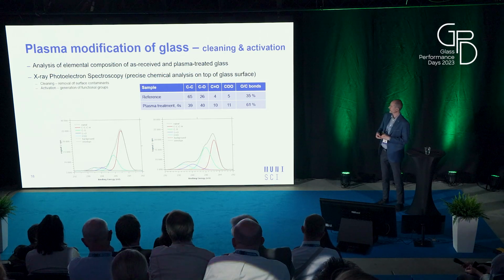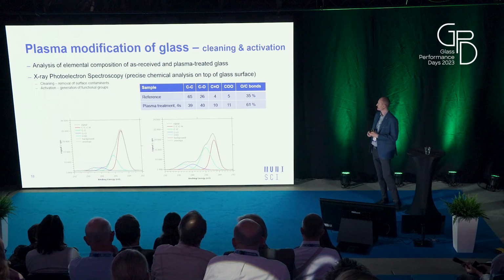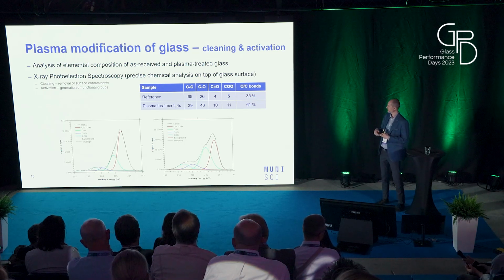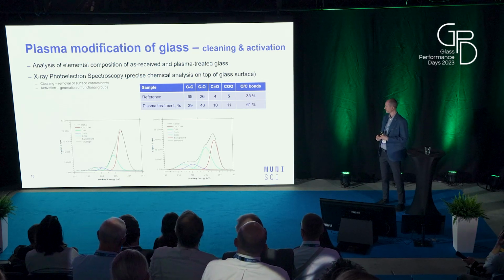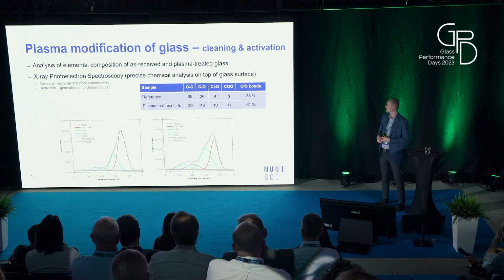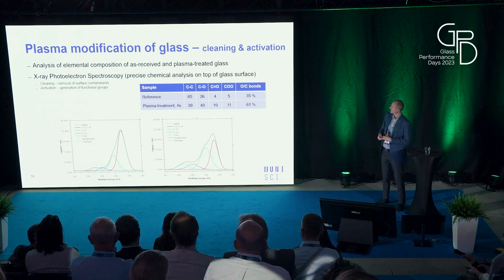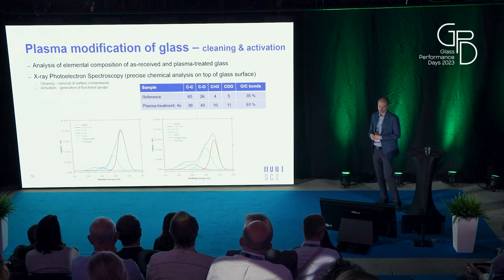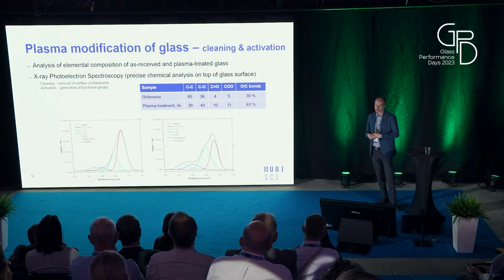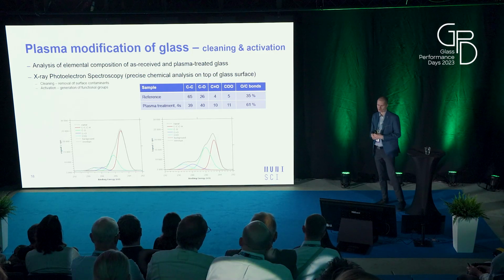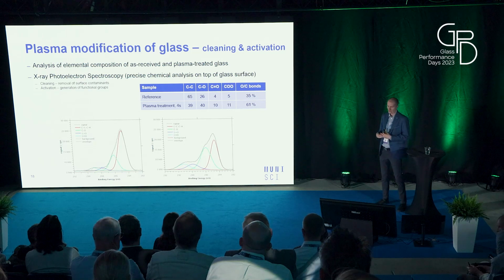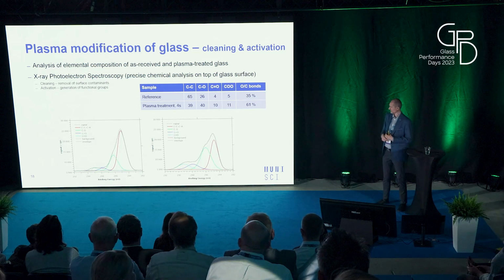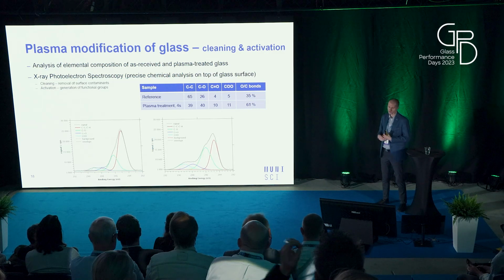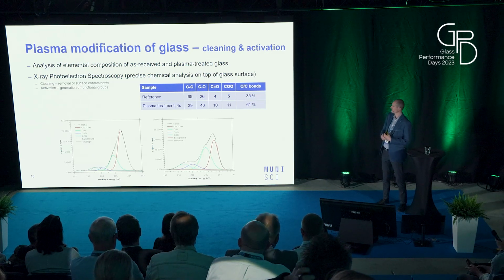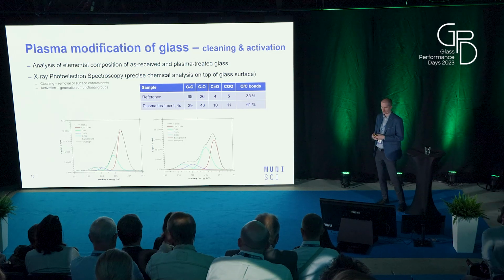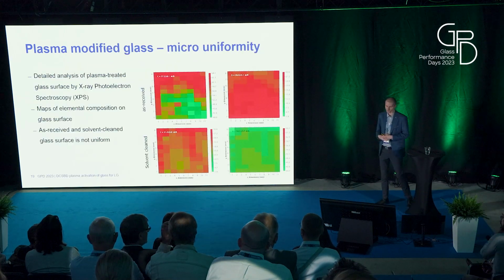And we calculated again the oxygen to carbon ratio, based on the ratio of hydroxyl and carbonyl groups related to pure carbon bonds. We see that on plasma-treated glass the content of oxygen bonds on the surface is more than 60%, and we observe this change only after 4-second treatment. In comparison, the reference sample is at roughly half of this value.